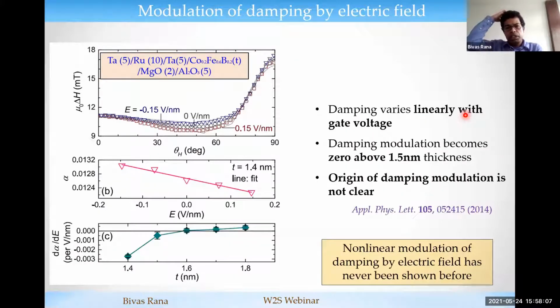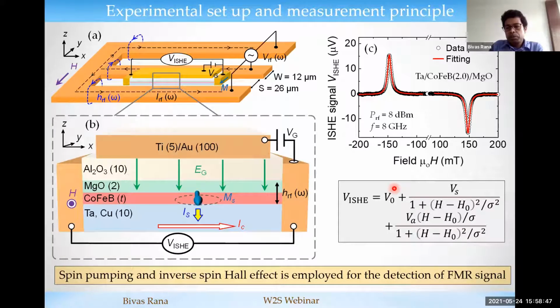Previously, Professor Hideo Ohno's group showed that the damping constant can be tuned by gate voltage, linearly proportional to the electric field. That means you can not only change the perpendicular anisotropy in the system, but you can also tune the damping constant. But the main observation in that study was that the damping modulation becomes almost zero when the thickness of cobalt iron boron increases above 1.5 nanometer, and the origin of this damping modulation was unclear at that time. So here we studied the cobalt iron boron MgO system, and the nonlinear modulation of the damping by gate voltage is quite new, and it has never been observed before.